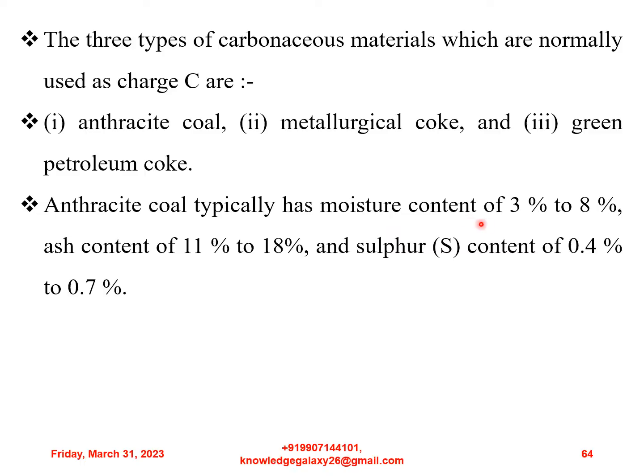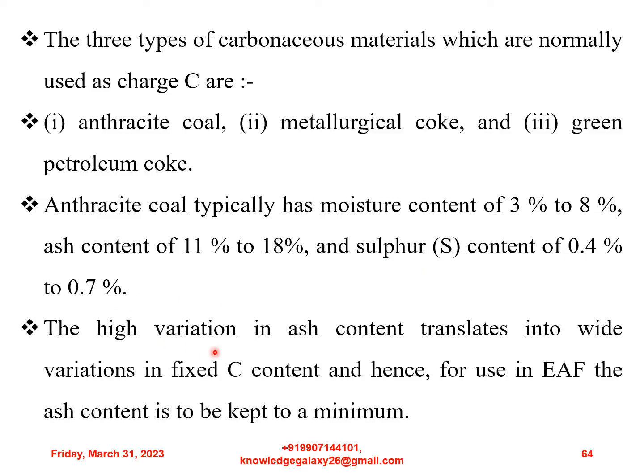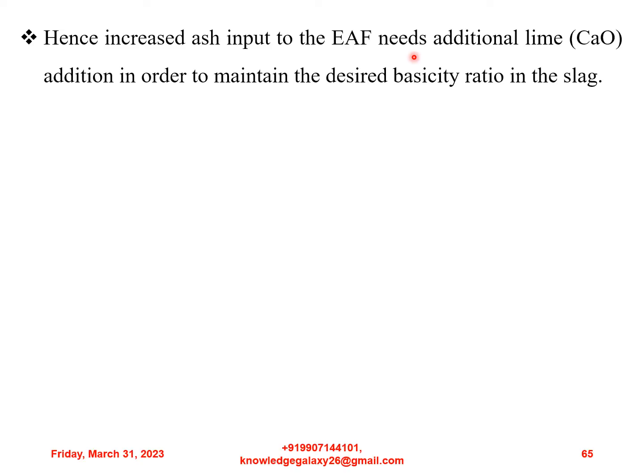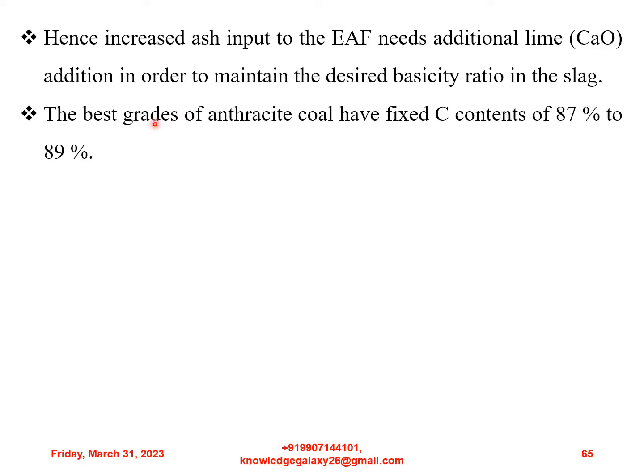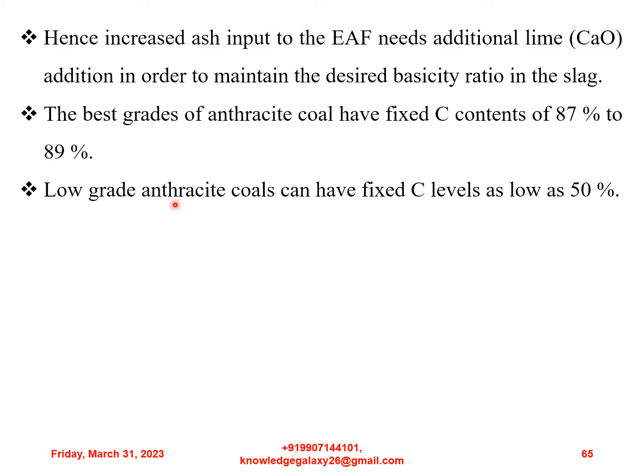Anthracite coal typically has moisture content of 3% to 8%, ash content of 11% to 18%, and sulfur content of 0.4% to 0.7%. The high variation in ash content translates into wide variations in fixed carbon content, and hence for use in electric arc furnace, the ash content is to be kept to a minimum. The ash consists primarily of silica, that is SiO2. Hence, increased ash input to the electric arc furnace needs additional lime addition in order to maintain the desired basicity ratio in the slag. The best grades of anthracite coal have fixed carbon contents of 87 to 89%. Low grade anthracite coals can have fixed carbon levels as low as 50%.